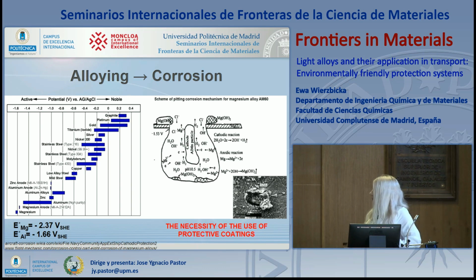Because magnesium and aluminium are among the most active elements, they are very sensitive to corrosion. In the presence of alloying elements, this effect can be even accelerated because of the formation of galvanic couples, where our metal will form the anodic side, be oxidized, and very quickly dissolve. Because of that, there is a big need to provide efficient corrosion protection for those metals.